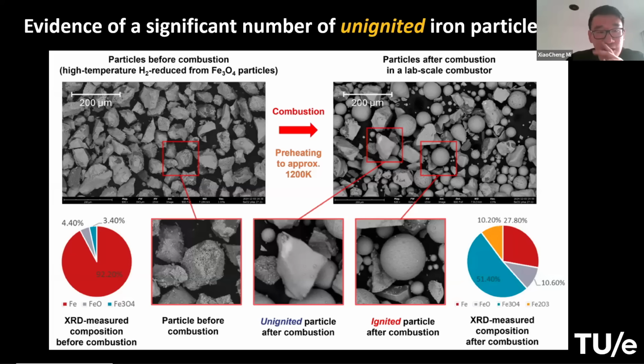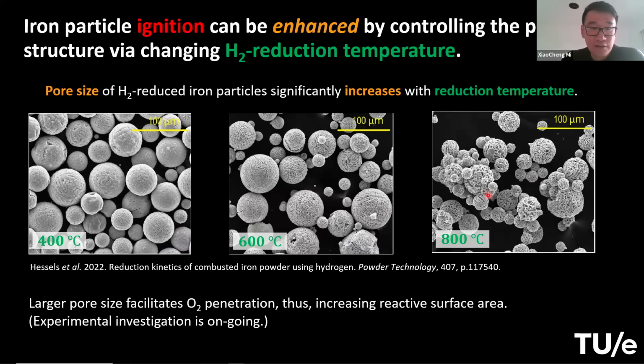Oh, you mean the one, because I think you are talking about the two different pores that I mentioned. The pores from reduction are like, for example, this one I'm showing here. That's in the solid phase of iron particles that is produced by hydrogen reduction, because the hydrogen reduction basically removes oxygen from it. So the molar volume of metallic iron compared to the molar volume of oxide, across the stoichiometric ratio, is less. So after reduction, you always end up with a porous structure using hydrogen, right? But what we are seeing is that the pore sizes are different at different temperatures of reduction. So this is the porous structure that I mentioned.